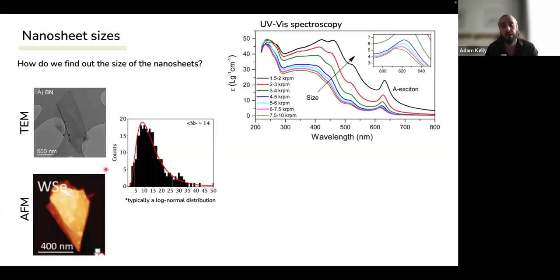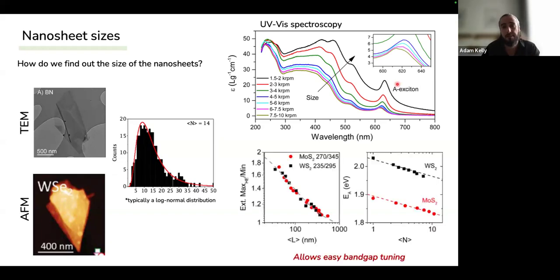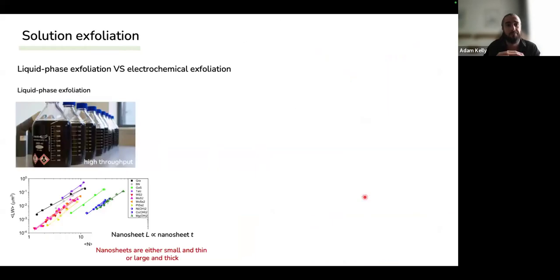And what we found was with a material like MoS2, for example, the excitonic features, like the A exciton, are related to the size of the nanosheets because of confinement effects around the edges. And what this means is we can just quickly take a dispersion after it's been sonicated, after we've applied our size selection techniques. We can do a UV-vis spectrum, and this can tell us, if we take something like the exciton position, we can correlate this with the length of the nanosheet. And this then allows us to tune the band gaps and tune excitonic features. So we can very quickly get information about the size of the nanosheets.